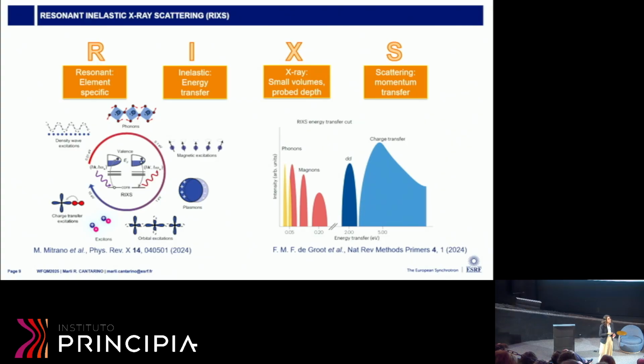In the case of magnons, they are very low in the energy scale, which for inelastic neutron scattering is not a problem because the resolution is usually very good, but for RIXS it can be a problem because our resolution is not as good. So we really needed a very good resolution to actually probe this when we start to dope the material.